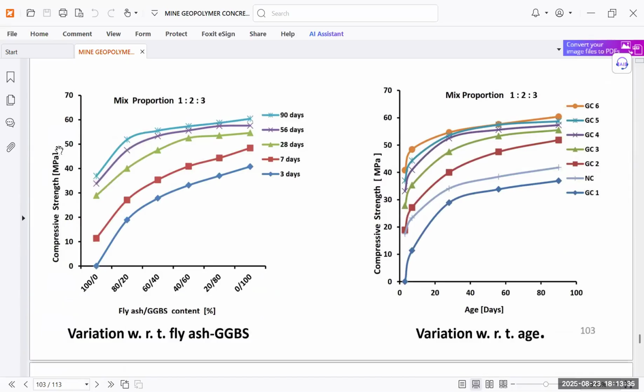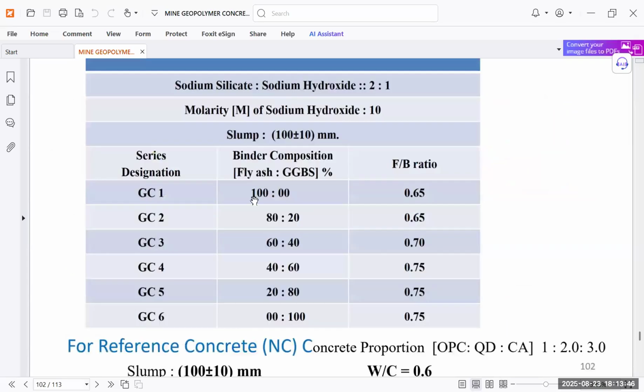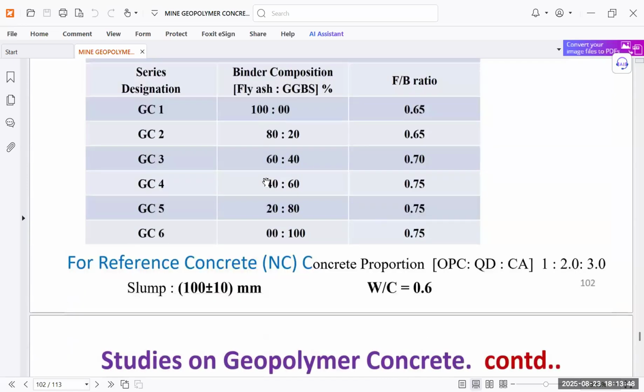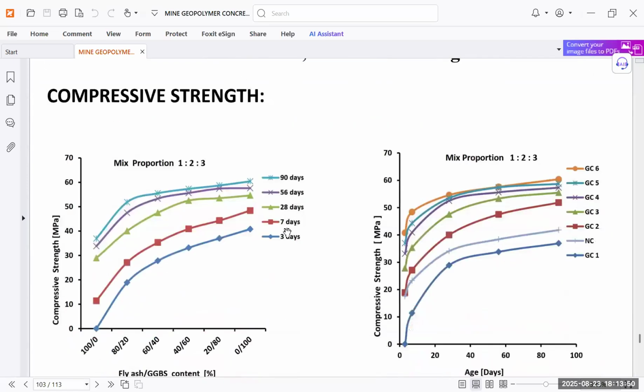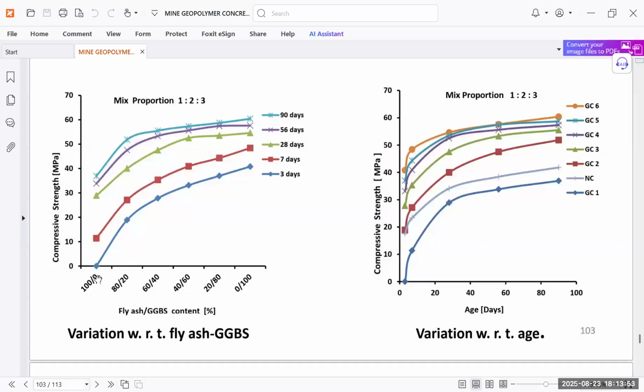Because we were using normal concrete earlier, that is why we have compared both. You can see the compressive strength here. This is the fly ash to GGBS ratio, this is the age in days, and this is the variation with respect to age and with respect to fly ash or GGBS. The fly ash to GGBS variation we have taken is 100 to 0, 80 to 20, 60 to 40, 40 to 60, 20 to 80, then 0 to 100. So for these variations, we are seeing the strength at different ages.